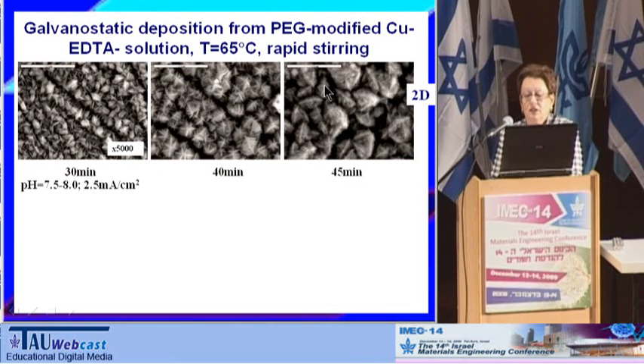The modified copper deposits are predominantly constituted of plate-like or octahedral-shaped grains. The grains, in turn, are assemblages of small, closely packed nanocrystallites, the size of which was about 35 nanometers, as we determined using the XRD tests. The longer the deposition, the larger the grains, and many of the grains approach the size of 5 micrometers.